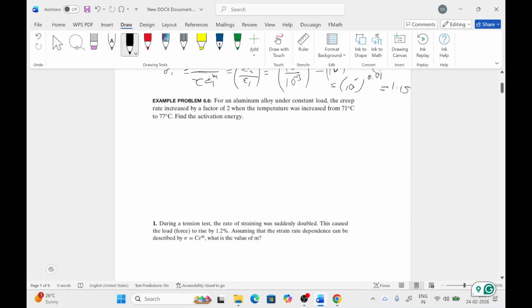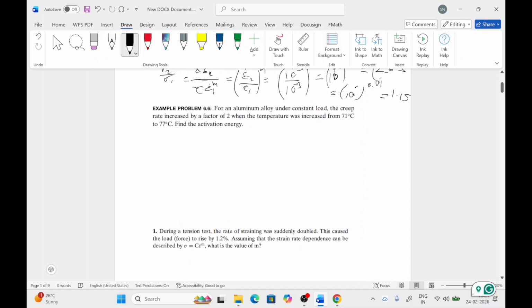So we'll go to the next problem. In this question, for an aluminium alloy under constant load, the creep rate increased by a factor of 2 when the temperature was increased from 71 degrees Celsius to 77 degrees Celsius. So find the activation energy. So here creep is given. This behavior of the material also depends on the strain rate and temperature.